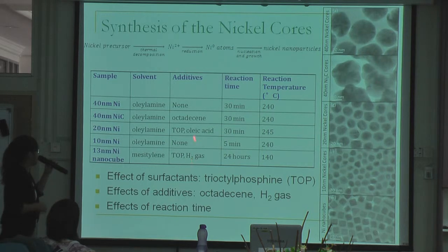When I reduced the reaction time from 30 minutes to 5 minutes, I was able to prepare nickel nanoparticles of about 10 nanometers in size. And finally, preparing the nickel nanocubes actually involves a very special combination of reaction conditions that was developed not by me but by one of my colleagues in the same research group.